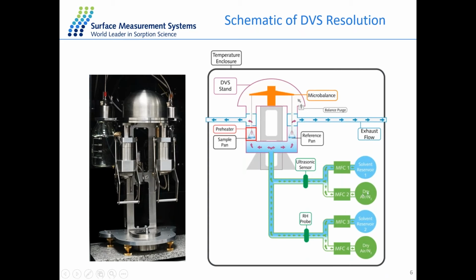The carrier gas for the system could be nitrogen or dry air, and the mass flow controllers inside the system will control the flow of the carrier gas with the saturated vapor in ratio to get a certain level of humidity. And this mixture will be detected by our sensors here: the speed of sound sensor for the organic vapors and the Rotronic probe for the humidity. These sensors ensure the generated humidity or partial pressure matches the target values.